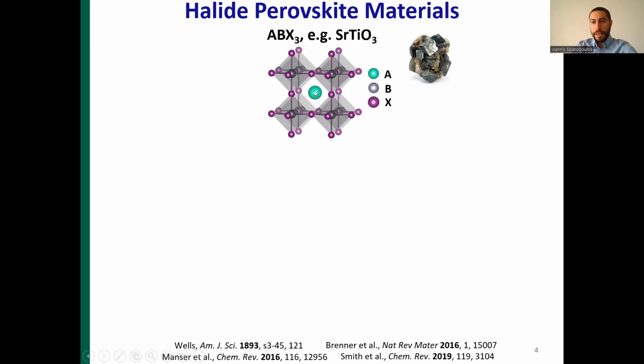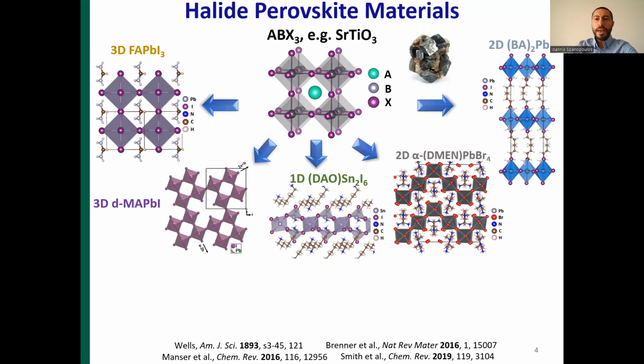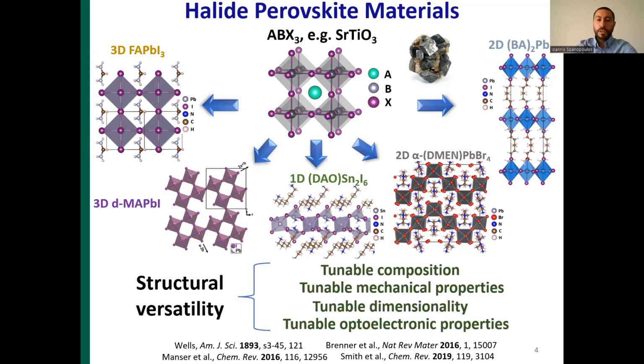If the A-site cation is replaced with bulky organic countercations, then a whole new family of hybrid halide perovskites emerges, each one with unique optoelectronic and mechanical features. This is an example of the 3D formamidinium lead iodide perovskite, where formamidinium is the countercation that resides in the cuboctahedral cavities. This is the family of the 3D defective MAPbI-based perovskites, 1D, 2D corrugated type perovskites, and 2D Ruddlesden-Popper type perovskites. This structural versatility allows us not only to tune the dimensionality, but also to fine-tune the composition and the mechanical and optoelectronic properties of the corresponding materials.